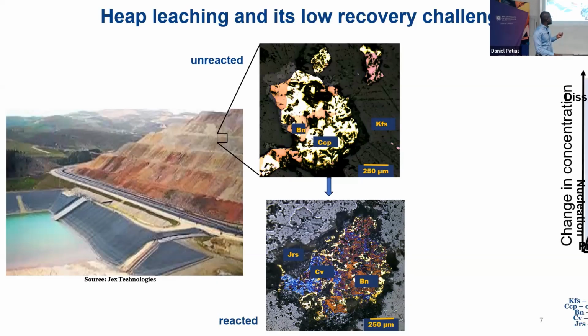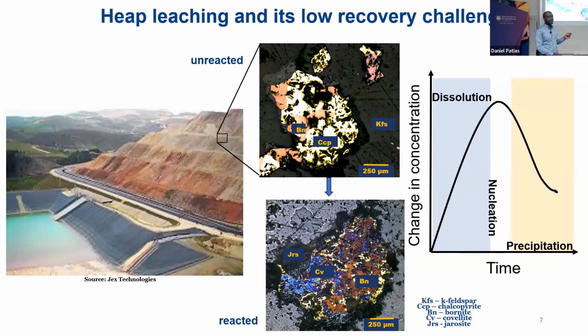If we translate what's happening in these two images onto a graph of changing copper concentration per time, what we observe is for the fresh surface, initially there is high dissolution, so you get much more copper in solution. But the very minute these phases start to form, there's nucleation of the phases, there's precipitation, and that causes a decline in the amount of copper that you are reporting to solution.